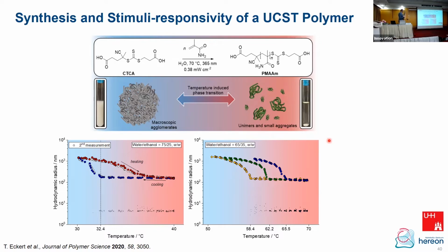And he also used photo-RAFT polymerization to synthesize polymethacrylamide. And somehow that works. This is nice. It shows an upper critical solution temperature. But what is not so nice is shown here on this plot, where you see three curves. It was the same original material. You heat it up, you cool it down, heat it up, cool it down, and always you see another transition. Why? The UCST is going down with the number of cycles.